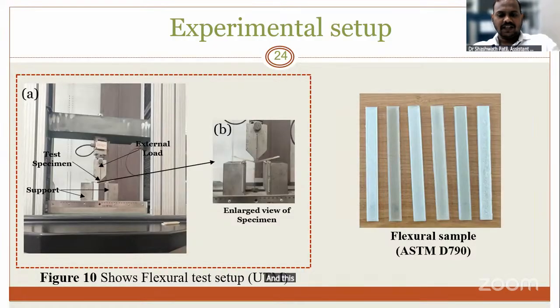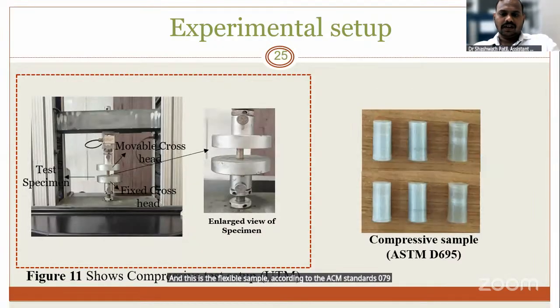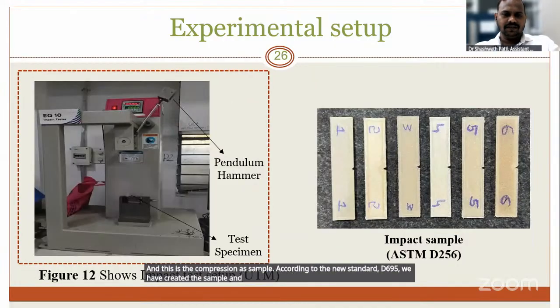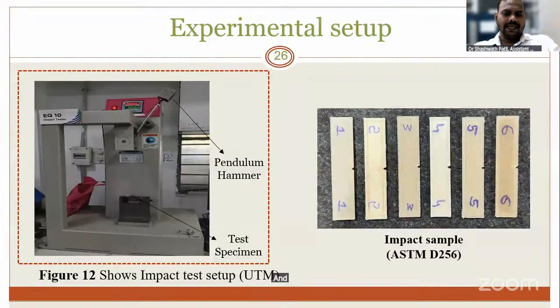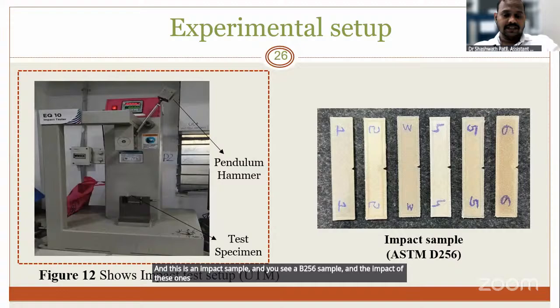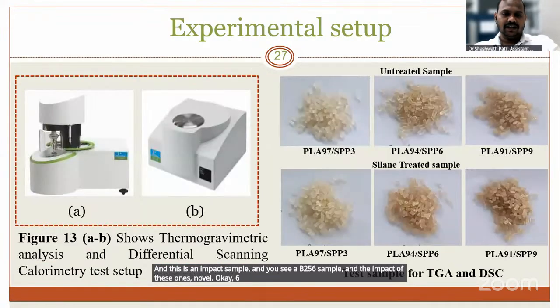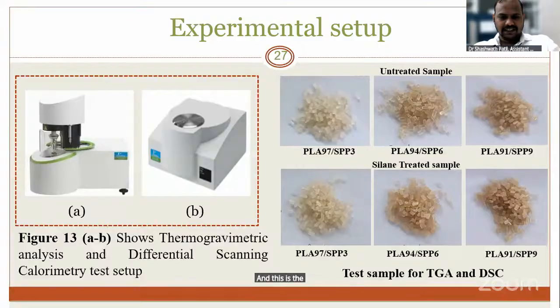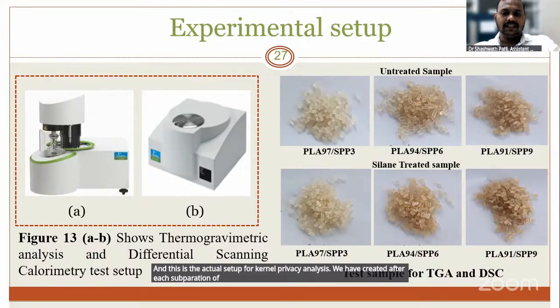And this is the flexural sample according to the ASTM standard D790. And this is the compressive test sample. According to the ASTM standard D695, we have printed the sample and placed it in the UTM machine. And this is the impact sample, ASTM D256, and for the impact strength we have printed 6 samples. And this is the experimental setup for thermogravimetric analysis. We have prepared it for each composition of untreated samples and treated samples.